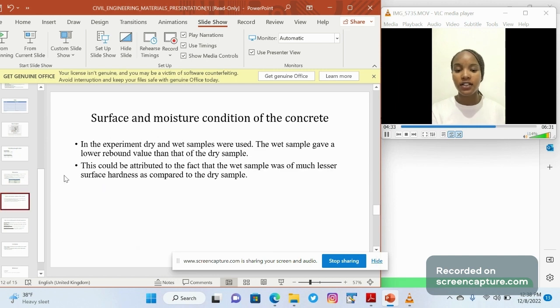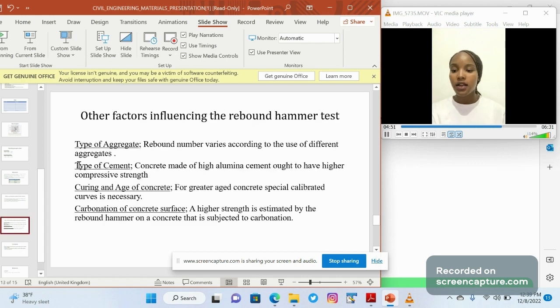The main factor that caused the difference in the cube strength is the moisture condition of the concrete. This is because the wet concrete cube has much lesser surface hardness compared to the dry concrete sample. Other factors that can influence the rebound number are the type of aggregate, because the rebound number varies according to the aggregate that has been used, the type of cement, because concrete that is made of high alumina is ought to have more compressive strength, curing age of the concrete, and carbonation of the concrete surfaces.